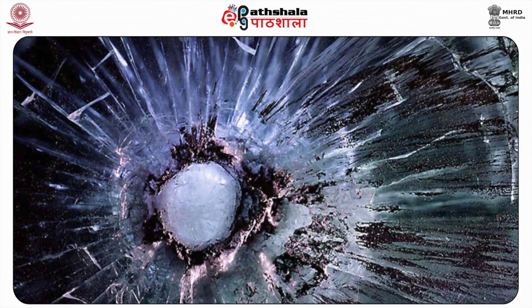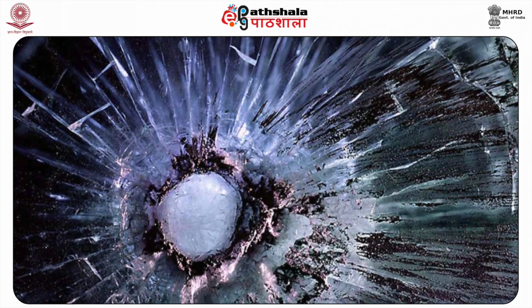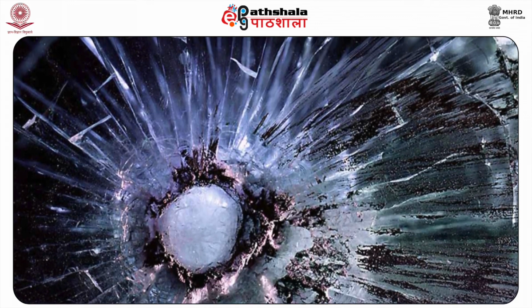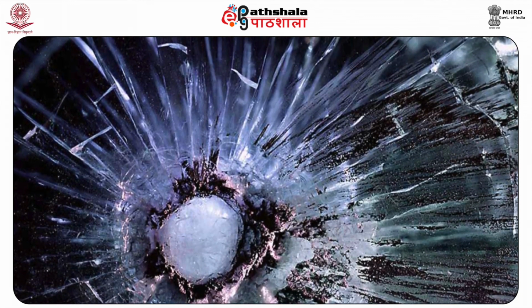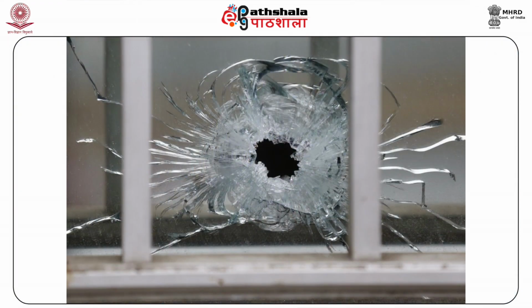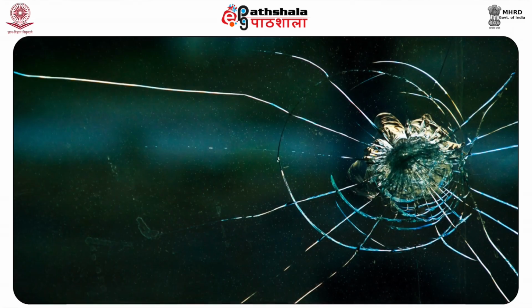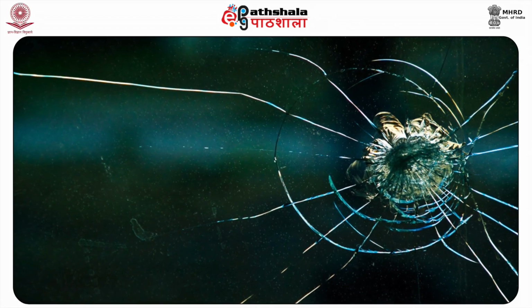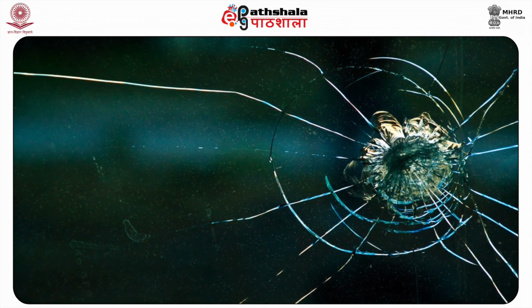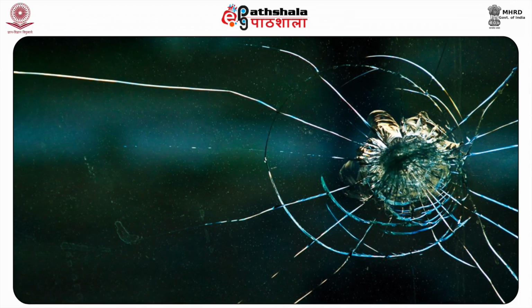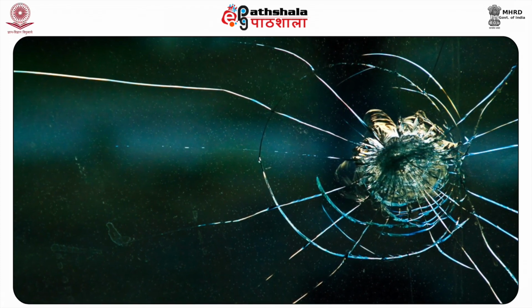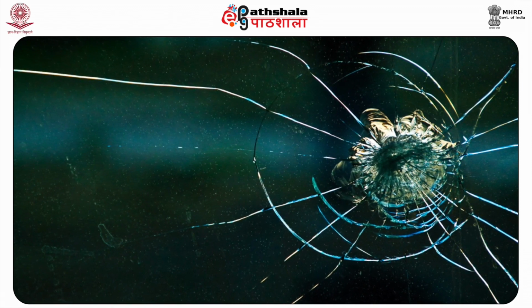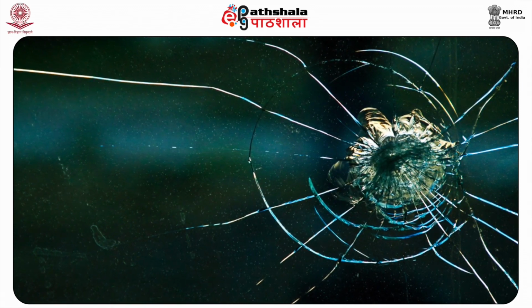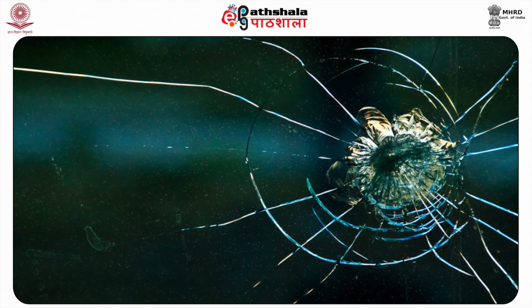A high velocity projectile, such as a rifle bullet, will yield a small hole with minimum flaking around the circumference. A slow moving bullet, however, delivers a more irregular hole with substantially more flaking. If an intermediate target has reduced the velocity of the projectile to even below 200 fps, the glass may show evidence of tension propagated fracture with no crater formation.